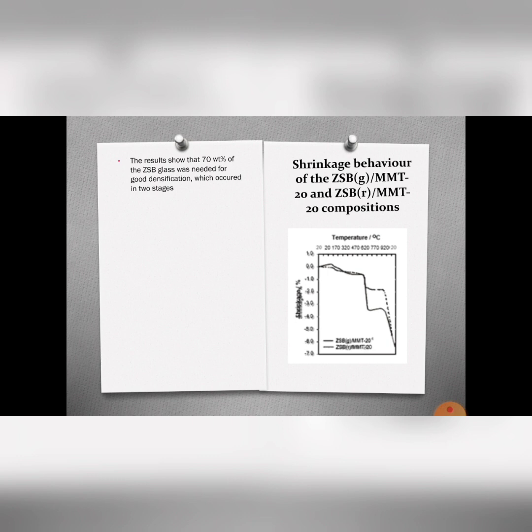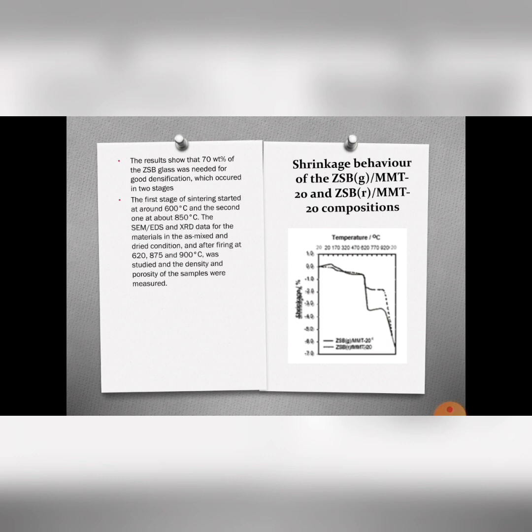First, this picture shows that 70 wt% of the ZSB glass was needed for good densification, which occurred in two stages. The first stage of sintering started at around 600 degrees Celsius and the second one at about 850 degrees Celsius. The SEM, EDS and XRD data for the materials in the as-mixed and green condition, and after firing at 620, 875 and 900 degrees Celsius, were studied, and the density and porosity of the samples were measured.